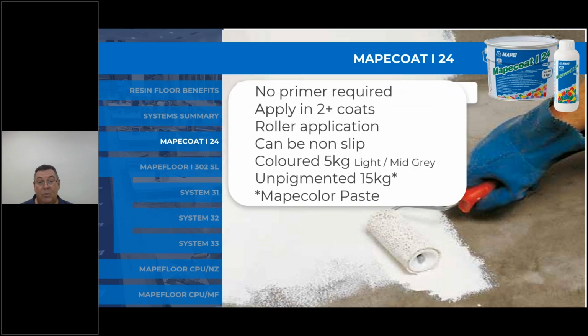There's no primer required, so you apply it in 2 or more roll coats. It can be applied in a non-slip, so if that's the criteria, a non-slip floor, and you are using Mapei Coat I-24, the first coat should be applied and the second coat broadcast and a seal coat over the top. Otherwise, broadcasting into the first coat can provide some compromise to the chemical resistance due to the thin layer on the top sealing over the aggregates. It comes in a 5 kilo pigmented container or in a 15 kilo unpigmented, where various coloured Mapei colour pastes are applied.